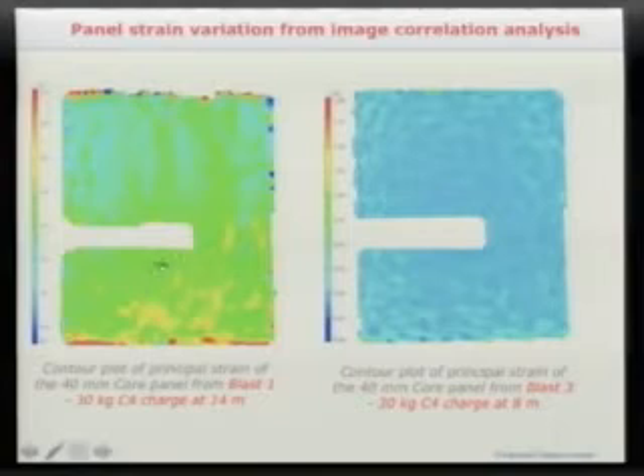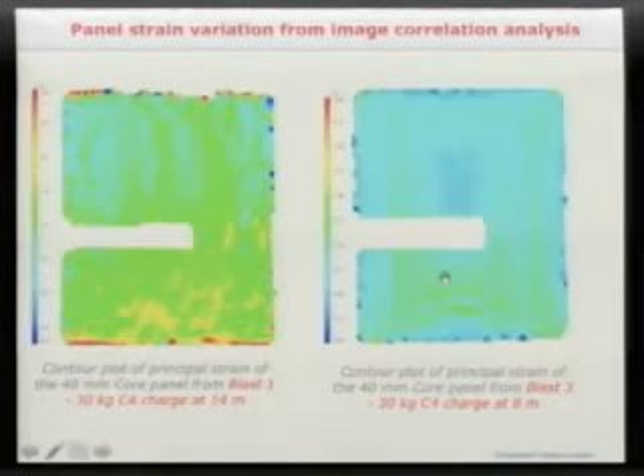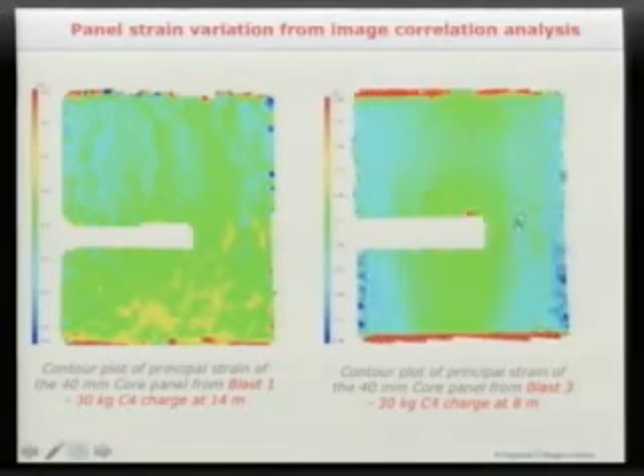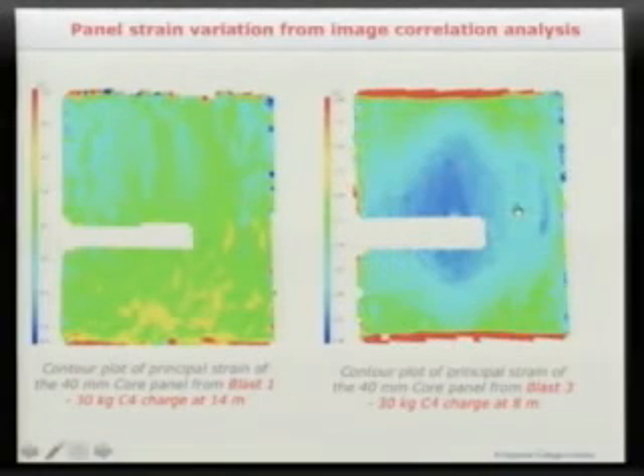And then we analyze these data to give you the strain plots. So you're looking at the principal strain here, and you'll see there's a high region of strain there in the middle. And this one, where the charge is very close, if you look carefully, you should just see a little bit of a discontinuity in strain there. And that's because the front skin has failed, the core has failed, the rear skin is still intact, but because you've got this core failure in front of that, it has an effect on the rear skin.